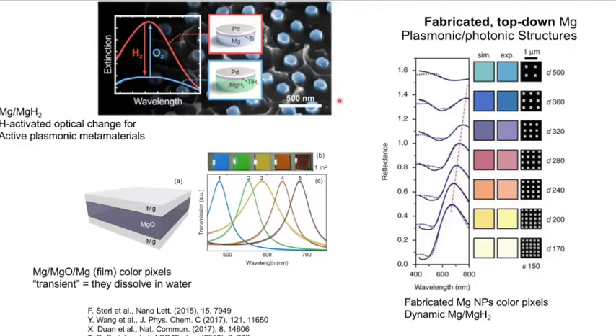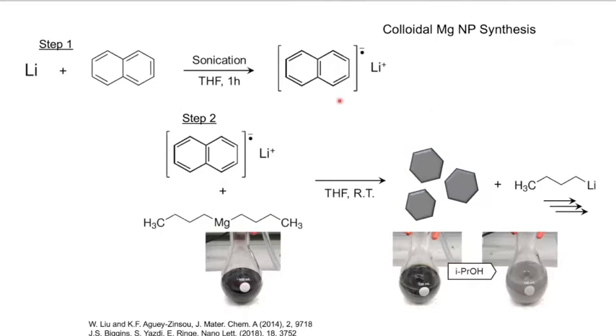If you work a little bit in plasmonics, you know that when you fabricate things, the quality of the material tends to be lower. They have rough surfaces, they have grain boundaries, and that all leads to higher losses, essentially, in the plasmonic resonances. So we're interested in making colloidal structures, single crystal nice structures. And what we did is that we turned to the literature of hydrogen storage. And these people had figured out how to make magnesium nanoparticles.